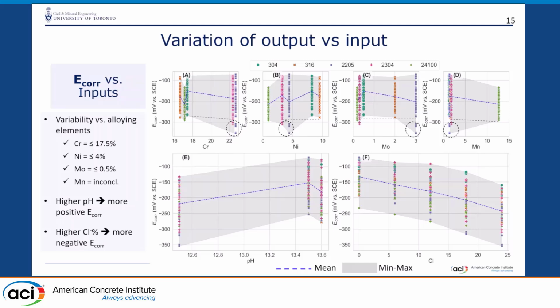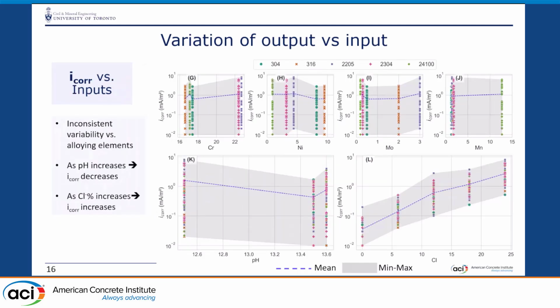Nickel plateaus somewhat, if I can say that, at around 4%. Molybdenum does the exact same thing. Actually, this goes the opposite way, becoming more negative. And then manganese follows the same trend as molybdenum. Now, the difficulty here is isolating each of these elements. So take it with a grain of salt, but it's just to show you the concept that we're going with.